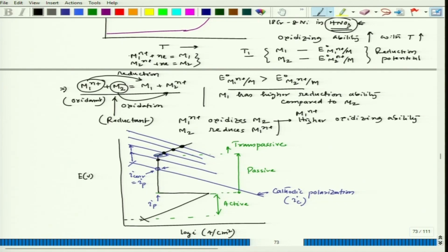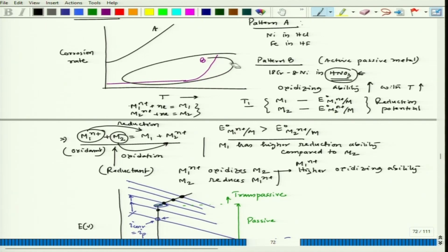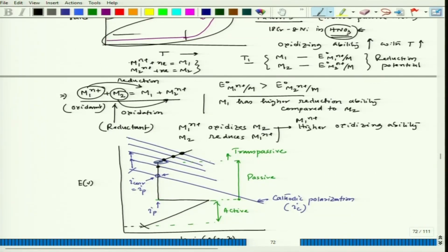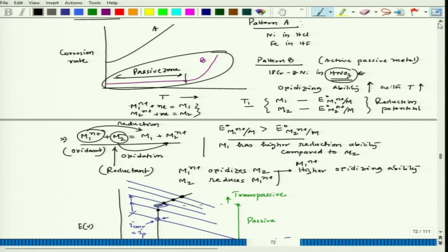After maintaining this passive portion, it goes to the transpassive zone. Definitely once it goes to the transpassive zone, the corrosion rate again increases. So, this is the behavior we could see here. Initially, up till this point it maintains the passive zone, and as the oxidizing ability increases, the reduction potential goes up, and the corresponding cathodic polarization line is cutting the active-passive anodic part, initially in the passive zone and then in the transpassive zone. So, the corrosion rate again increases like this.